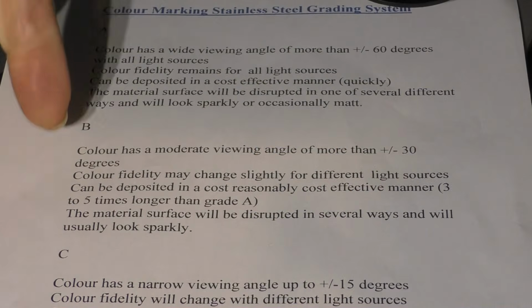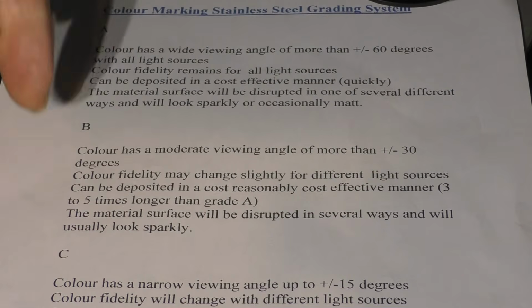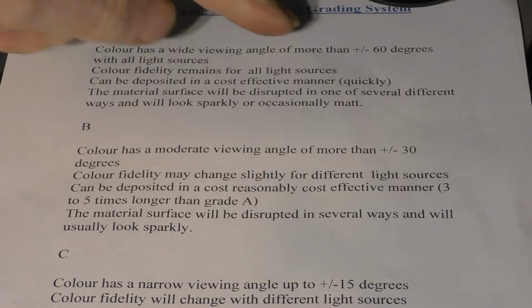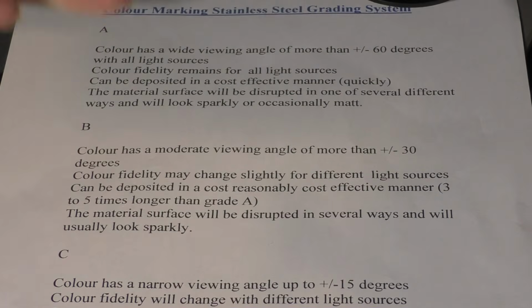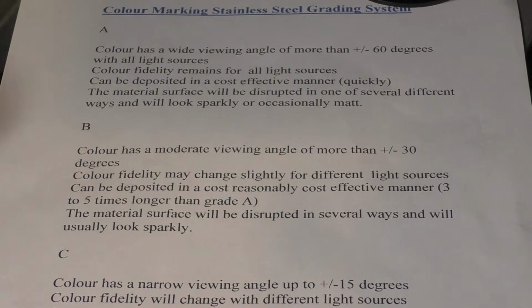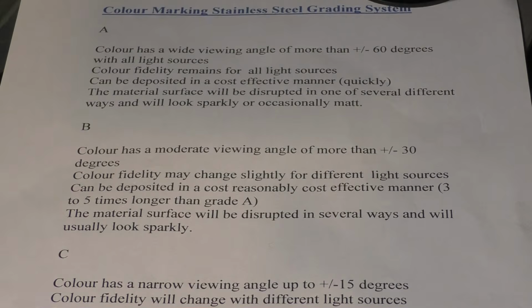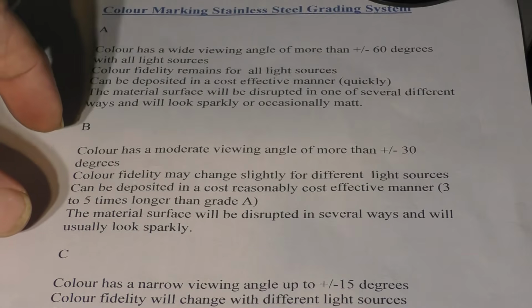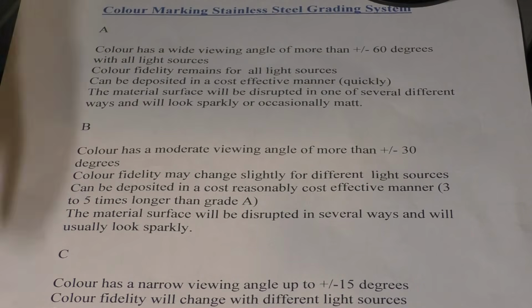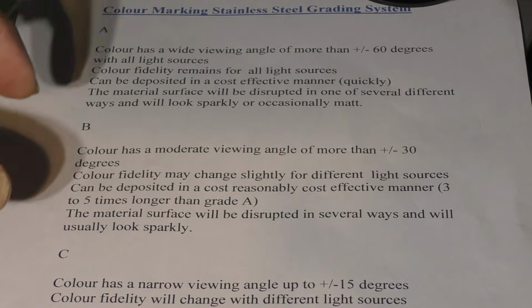So the factors for the other grades are similar, but for instance a B grade, instead of plus or minus 60 degrees, I've nominally chosen plus or minus 30 degrees based on my experience. It's very likely that they could be as much as plus or minus 60 degrees. They could be A grade viewing, but they could be incredibly long as far as production time is concerned, which throws them out of the A grade and puts them into a B grade where you may want to use them. It's up to your judgment as to whether or not it's cost effective.